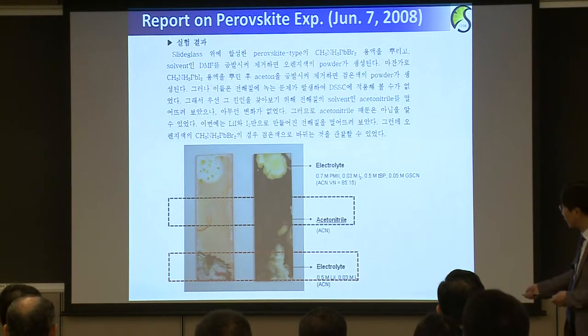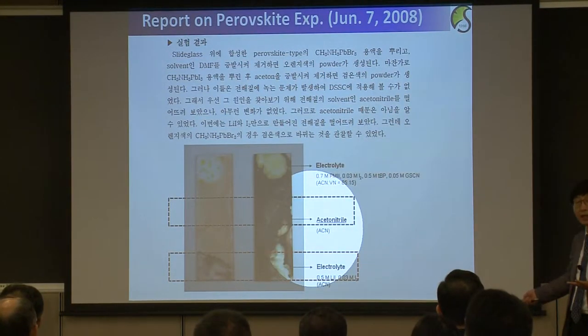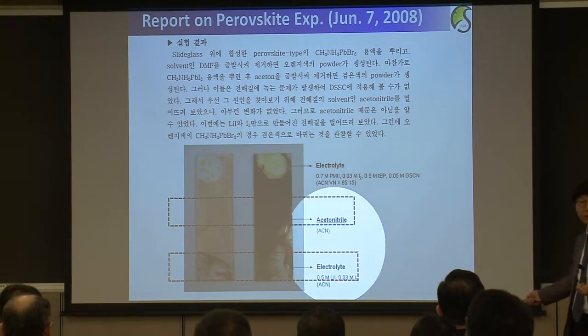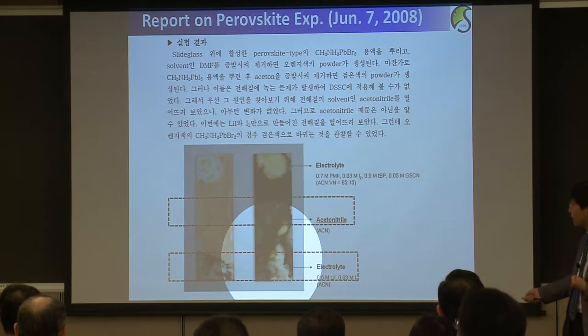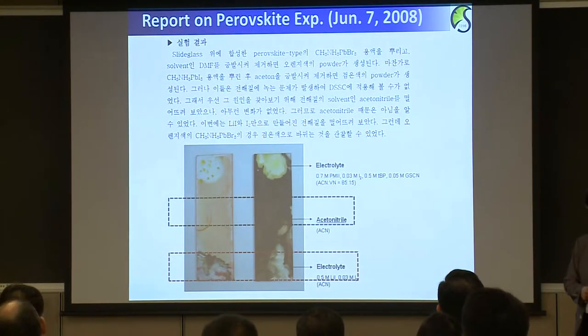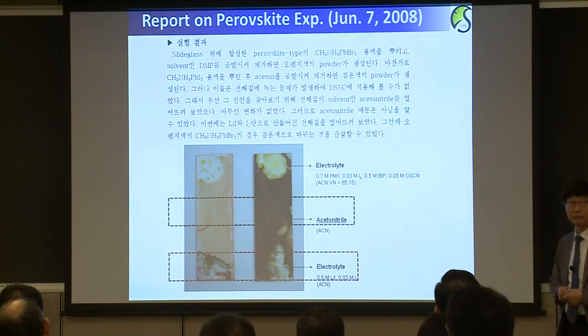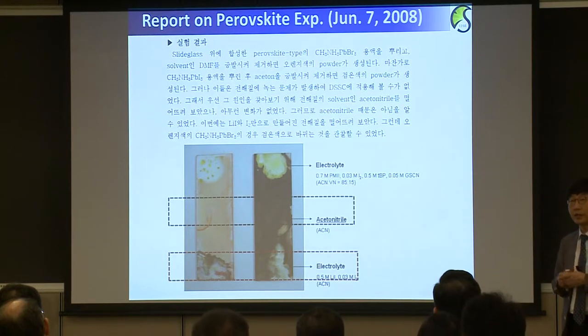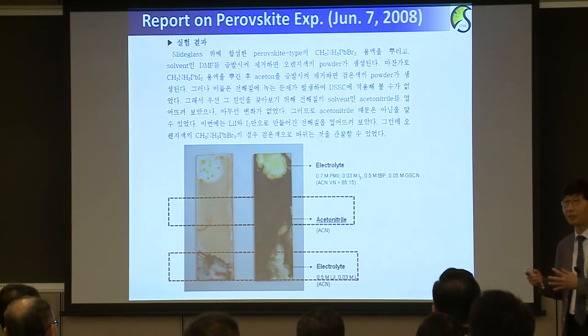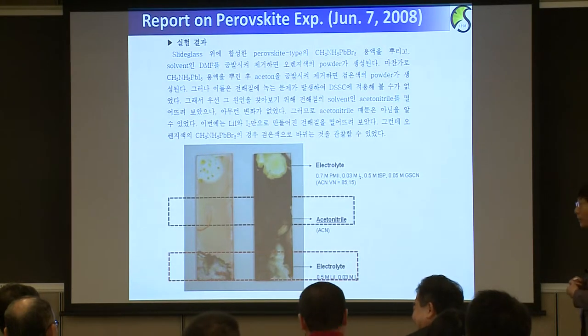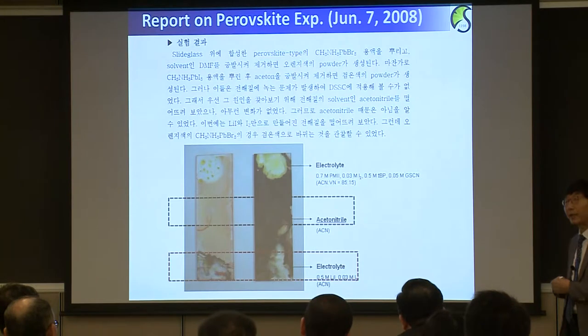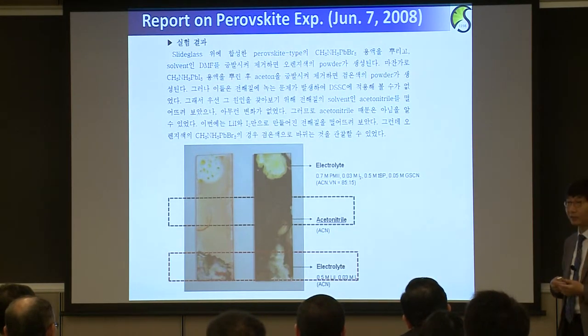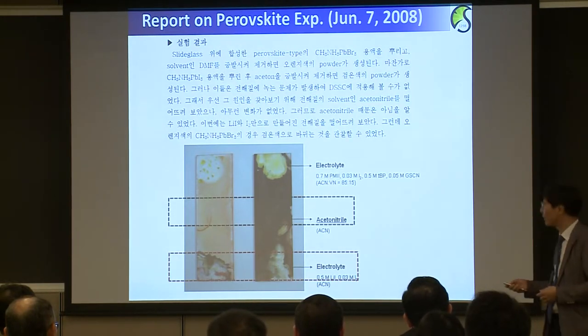And then she dropped the electrolyte, because at that time we used a liquid electrolyte containing lithium iodide and iodine. And then she found that this perovskite immediately disappeared, dissolved. And also in the bromide case there is some exchange of the anion. So she recommended to me that this material seems to be garbage because it's quickly dissolved out. So it's not useful for the dye-sensitized solar cell. And then she left to the National Renewable Energy Laboratory to do another postdoc work.